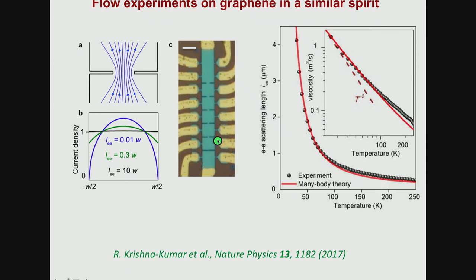They decided to just make constrictions. And they made these constrictions of different widths, and they studied at different temperatures. And the idea there is that the correlations in a hydrodynamic fluid can, in some circumstances, make that fluid flow through that constriction more effectively than a ballistic one would. So the viscosity gives some channeling, is the idea.